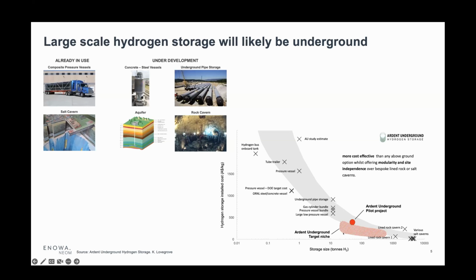Underground pipe storage, anywhere upwards of 10 to 100 tons. And these types of pipe storage systems, where you basically line a hole in the ground, you can get anywhere from 100 to 1,000 tons of hydrogen. After that, when we're talking about really large amounts of hydrogen, upwards of nearing 10,000 tons of hydrogen, you're going to have to go to a natural structure like a salt cavern or a network of salt caverns.